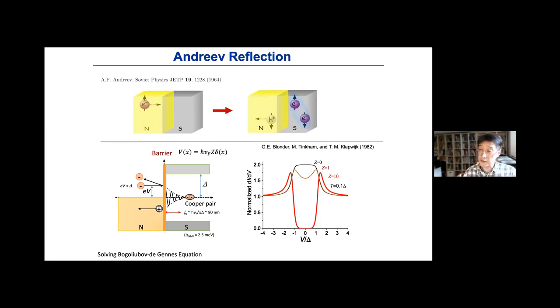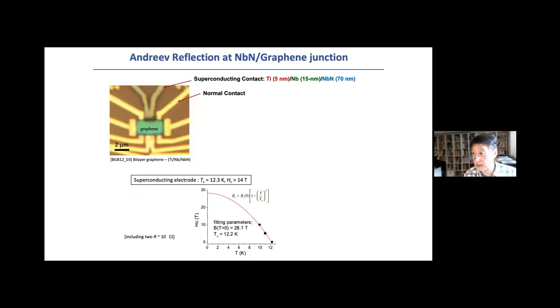So the idea is, first, can we actually build up the superconductor and the graphene channel and demonstrate whether the Andreev reflection can be measured under the presence of the magnetic field. Here's an example where we use graphene, and as the superconductor, we particularly use the combination of niobium and niobium nitride. We use titanium as a sticking layer, and this combination provides extremely efficient contact to the graphene through the titanium layer, but the presence of the niobium nitride gives us quite high Hc2.